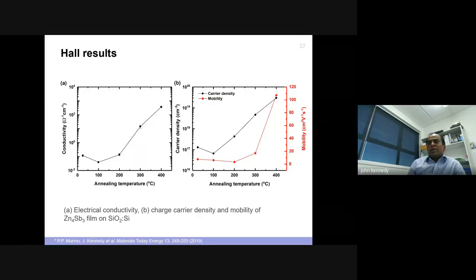So what happens in terms of conductivity? Again, we do a simple Hall probe. We look at the conductivity. As you can see, if you anneal at 400, the conductivity goes up, the carrier density goes up, and the mobility is also going up. So we are able to manipulate it, and this is when you see increased electrical conductivity above 300 degrees, and simultaneously increased charge carrier density and carrier mobility. This is great. This is a top layer where you're looking for the efficiency.